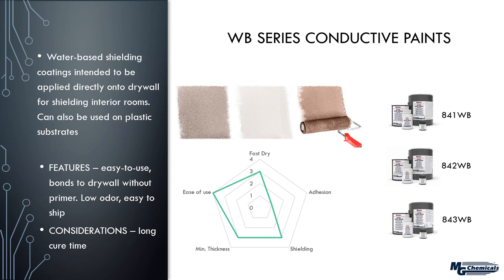The consideration here is that they do take a long time to cure. And that's because with any water-based product, you need to let it first cure at room temperature before you apply any heat. This is just to give the film enough time to properly form. If you rush it, you may in fact cause some cracking, and any kind of gaps in the film will result in poor shielding.